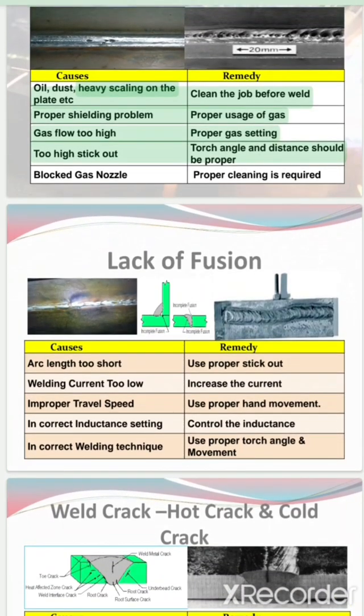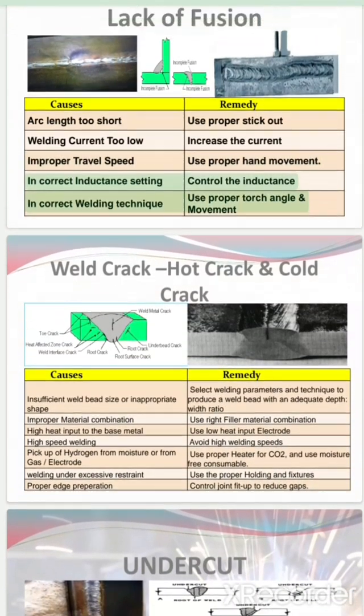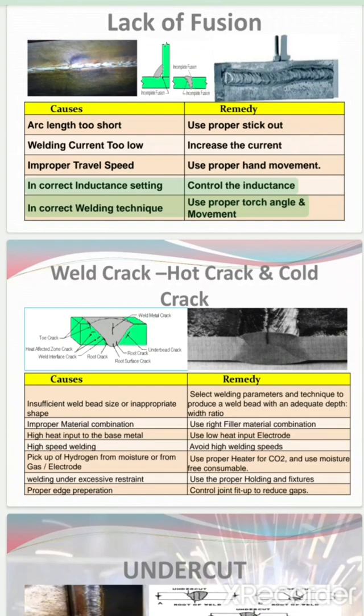Shielding problem: use proper gas setting, gas flow too high. Stick out, torch angle and distance should be proper. Blocked gas nozzle, proper cleaning is required. Lack of fusion. Causes and remedy: arc length too short, use proper stick out. Welding current too low, increase the current. Improper travel speed, use proper hand movement. Incorrect inductance setting, control the inductance. Incorrect welding technique, use proper torch angle and movement.